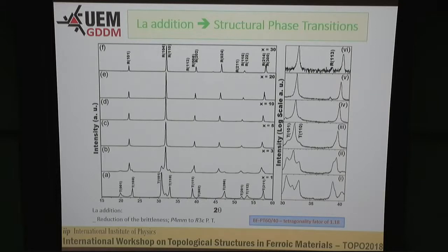Okay, to see these properties, we created solid solutions of BFPT, where we replace with lanthanum to control the tetragonality factor of the samples. You have a phase transition from a purely tetragonal sample to a purely rhombohedral sample if you have 30% of lanthanum in a site of this material. This material without lanthanum has a tetragonality factor of 1.18, 18% tetragonality. If you put lanthanum in the system, this tetragonality factor is decreasing, decreasing, decreasing. You have a phase transition to only a rhombohedral phase, and here you have something like a morphotropic phase boundary.